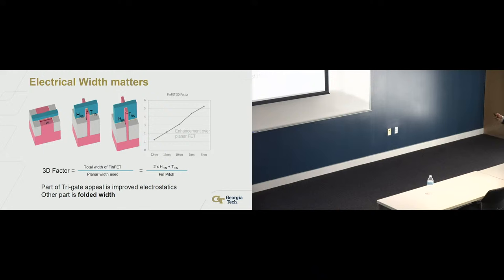But the interesting part that we found, and I don't have time to get into that, is that most of your current is now conducted on 110, because the crystal plane on the two sidewalls is no longer 100 like you have with the planar configuration. 110 has a very different piezoresistance property than 100 silicon, because piezoresistance is a tensorial quantity. It depends on the crystal plane. So you go back, you engineer the strain all over again, and long story short, for electrons, it turns out that if you put pressure vertically down, that will increase your electron mobility along the 110, because it's a transverse compressive strain, which is very different than that uniaxial tensile strain in the direction of current transport.